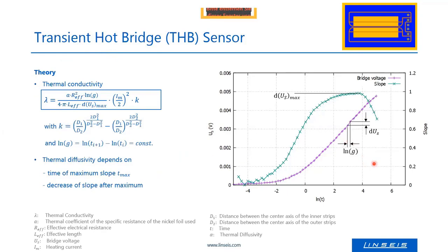But for now, it is okay to know that we get the slope from this delta U at the inflection point here. This inflection point can be seen when the first derivative of this curve is plotted; then we see a maximum here. At the maximum, we have this inflection point, and the slope is calculated by the delta of the bridge voltage divided by the delta of the logarithmic time between here and here. We have this slope, du divided by the logarithm of the time, but it's reciprocal. So it's inversely proportional to the thermal conductivity.